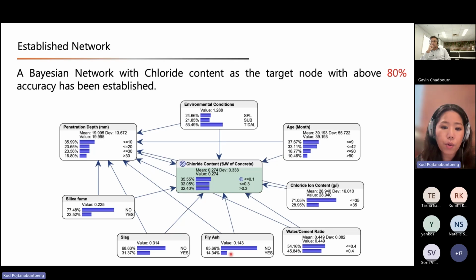Water cement ratio. At the moment, for the mix, we have silica fume, slag, and fly ash. We don't have enough data to detail the percentage of each of these components yet. We only put yes or no: yes, we have it, or no, we don't have it. And then the penetration depth. So this is how the relationship of each of the parameters and the chloride content at a given location would look. This is an example.